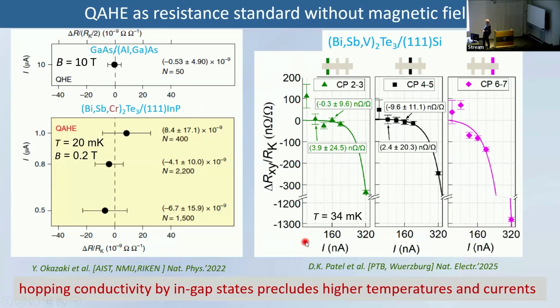And also that if you put high current, you have also a decrease of this precision of quantization. This data changes. If you put higher current, instead of the plateau, you get to another value. So we should work hard to get access to higher temperature and higher currents. And what is the reason that we need low temperature and we need low currents?